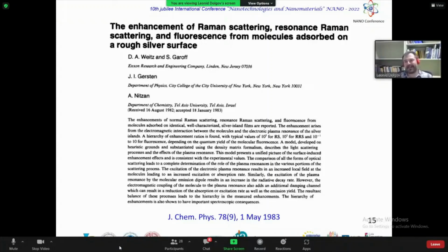But now I see that the answer is that the more constructive way is to couple the plasmon with emission, because if you couple with absorption, and you have a large Stokes shift between absorption and emission, this large Stokes shift already gives you a lot of ways for non-radiative processes, and these non-radiative processes will basically limit the plasmonic effect which we would like to see in emission.